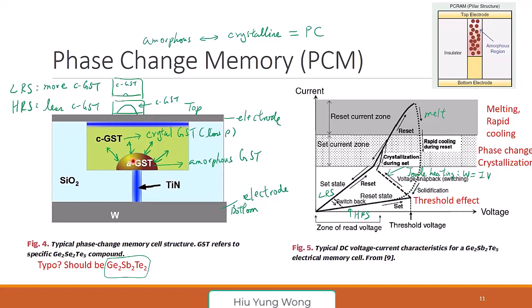So if you go from amorphous to crystalline, you heat it with high temperature, but not melt. So it gradually reorganize, heal it. If you want to change it back to amorphous, you heat it really hard, then it melts. And then suddenly remove the voltage. It cools down. Once it cools down, it will become amorphous because it's disordered. They don't have time to rearrange the atom from the disordered liquid. And that is phase change memory. And you see that the temperature profile control is very important. That's why people will do about how you can engineer this capping layer to reduce or enhance the heat dissipation. If this layer are not thermally conductive, it actually make it easier to make into amorphous. But on the other hand, it also slower because it take longer time to cool down. And that's all I want to say about this. Any questions? Try to ask. Anything not clear?